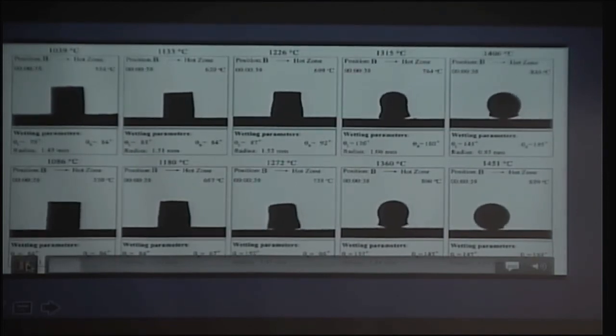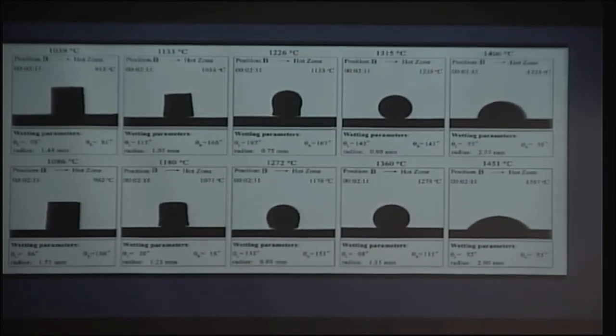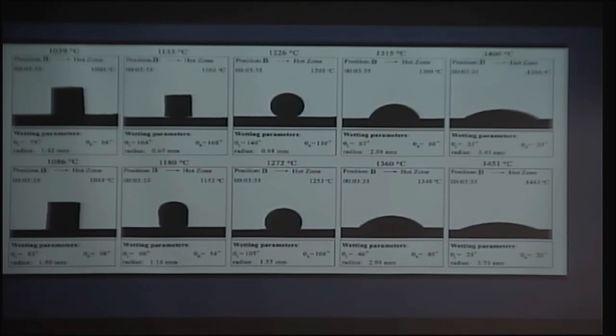So we started to work out a parameterization of the thermal fate of ash when you reheat ash particles. And what you see here is time series analyses of optical dilatometry in a high temperature furnace of how ash fuses or softens, actually only at the glass transition, and wets the surface of jet turbines.